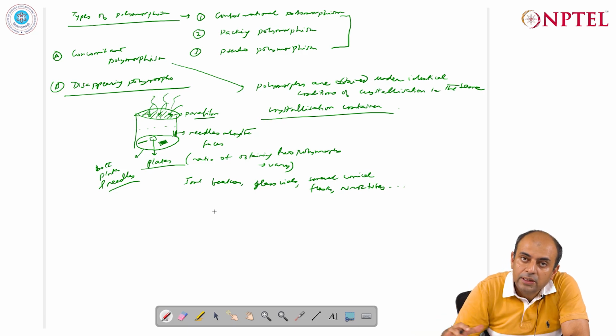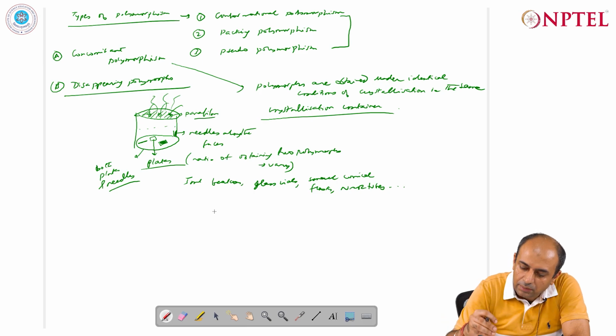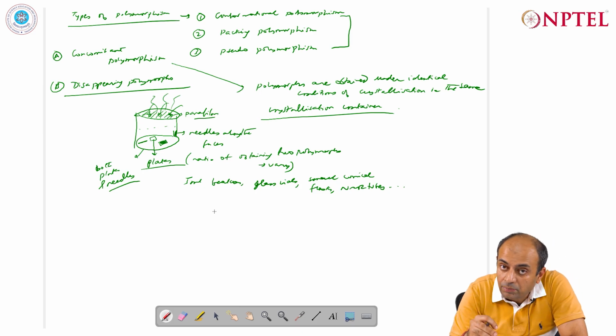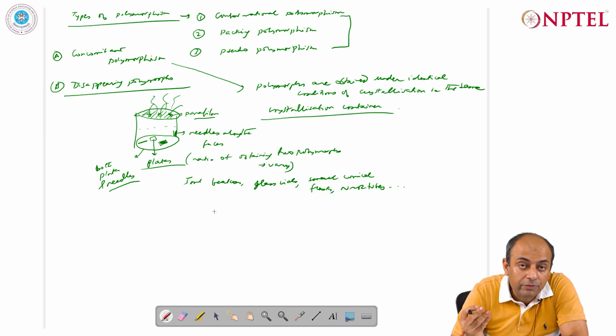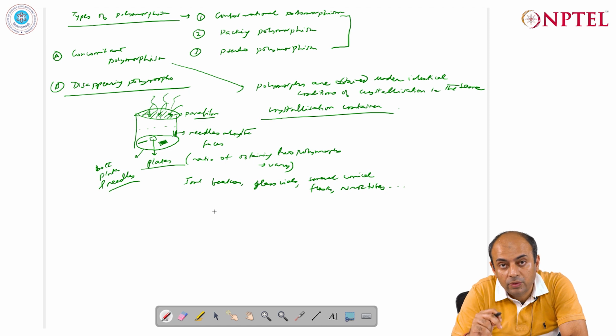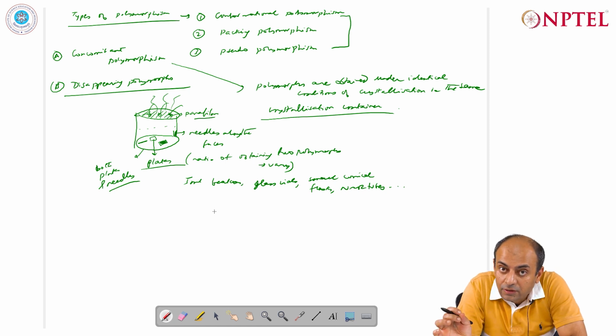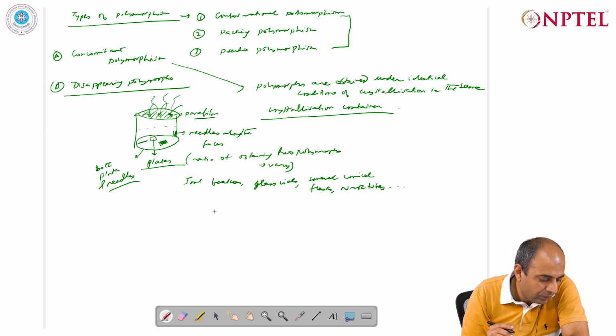So this field of crystallization is itself an independent research area, but when you do these crystallization experiments, the possibility of getting concomitant polymorphs does exist, and this is observed as different kinds of morphology. Sometimes you will see different morphology and also different colors. So you will see one is orange, one is light yellow, one is deep red, one is light orange. Sometimes you can get similar morphologies but different colors. So that is also indicative of color polymorphism and the possibility of having concomitant polymorphs in the same crystallization container.